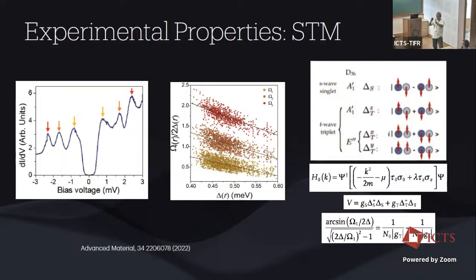For example, if you put a magnetic field in a system which suppresses the gap, they found that the Leggett mode energies simultaneously move outwards, which they argued means that for you to have a Leggett mode in your system out here, you cannot explain it by the presence of a conventional S-wave pairing mechanism. You need some unconventional pairing or some kind of a strong anisotropy to be there in your superconducting state.